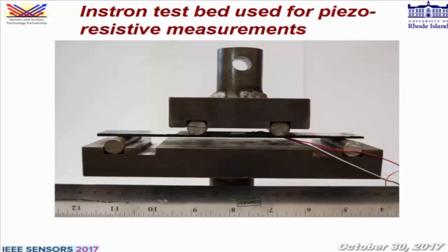This is the setup that we use. This is a custom-built 4-point test rig. Each of the little cylinders here are equally spaced apart, so that when we apply a load on this surface, it's uniformly distributed. The sensor itself has a strain gauge mounted so that we can measure the strain that we apply, and we force a current through, and with platinum wires extending out to a data acquisition system, we can measure the voltage drop across and relate that to Ohm's law to measure resistance.